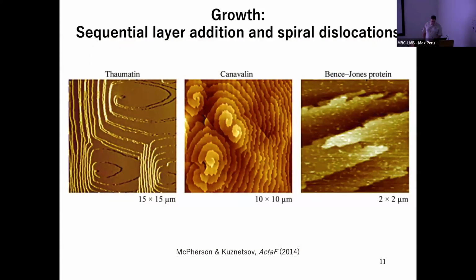It was shown with atomic force microscopy that multiple nuclei can appear on the surface of the crystal and become two-dimensional patches. This explains a main mechanism of crystal growth by sequential layers addition, as two-dimensional patches go tangentially and merge to form a layer. So because there are several 2D growths around the surface of the crystal, this is a constraint, and it's continuously creating step edges on the growing surfaces, which can lead to dislocation between spiral structures, and that turns to crystal imperfection.